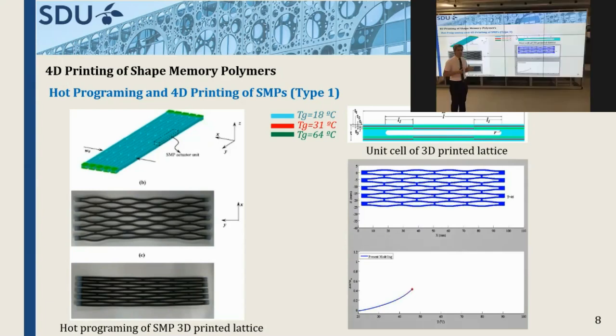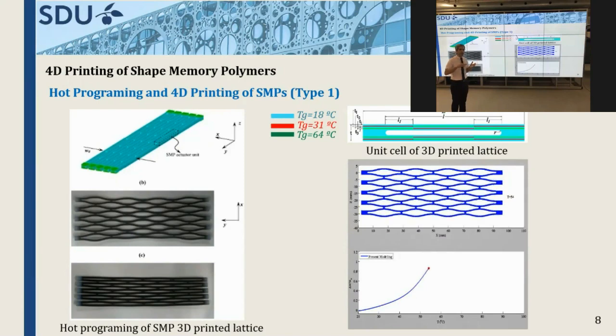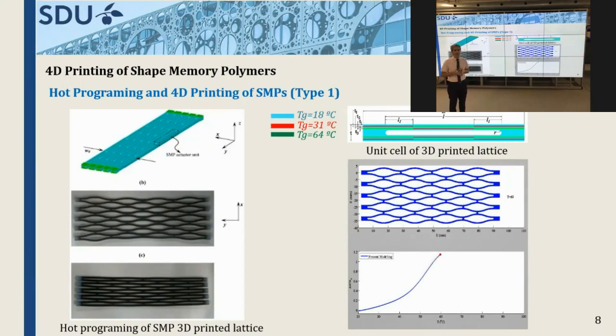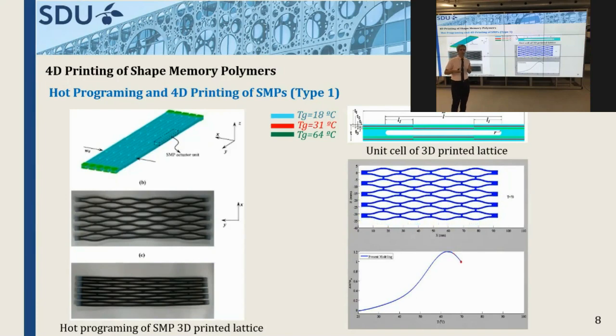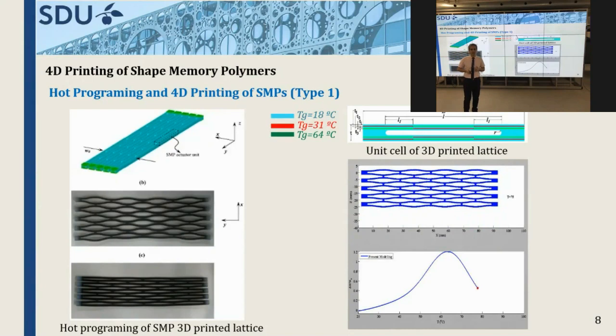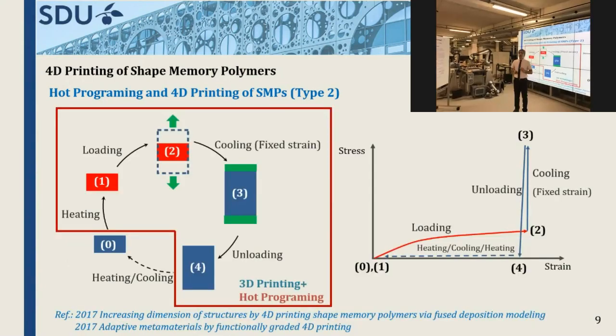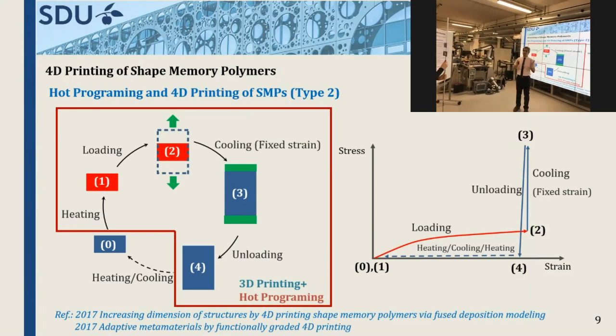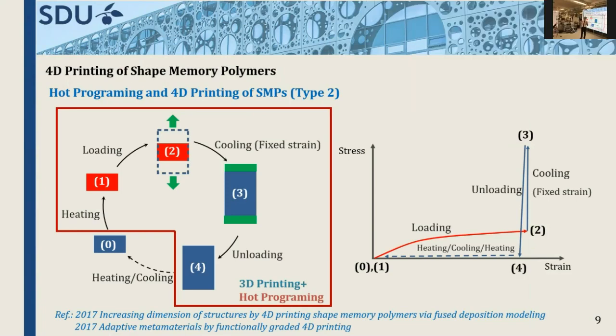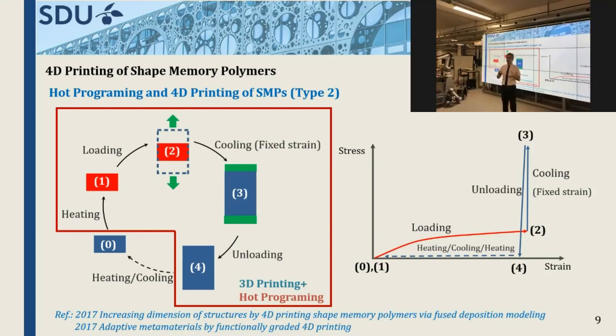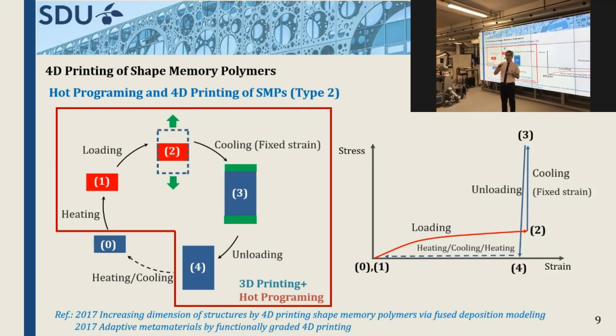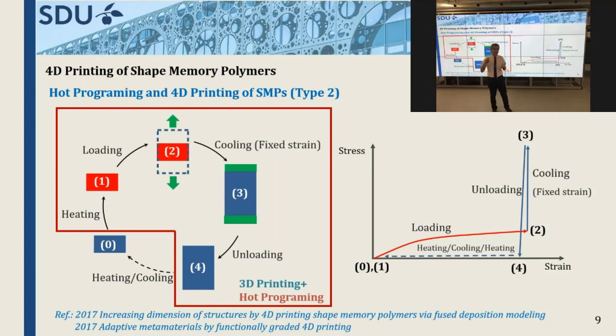As you can see, this lattice, by increasing temperature, is open. By increasing more at the higher temperature, this lattice will be closed. The sequence of activation of each layer can produce this opening and closing motion. The other effect of shape memory material in additive manufacturing is the programming inside of the 3D printer. It means that during printing, the programming happens at once. The 3D printer melts the shape memory polymer, and by moving, some deformation, some strain is induced inside of the 3D printer, and this configuration can be recovered by heating and cooling process.